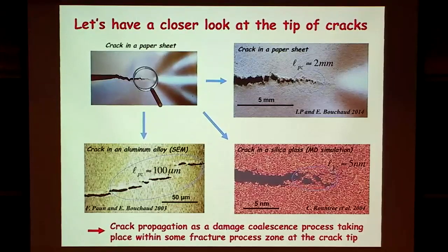Okay, I'll try to answer Srikanth's question. I guess when you look at these damage drops, they are random, I mean, the structure on them is random. However, once a damage front has appeared, or a damage drop has appeared, the next one is correlated, and the next one is correlated with it. Therefore, on scales much larger than these drops, you have correlated exponents, whereas under that scale you have just the random thing of the local structure. This is why you have the change in exponents physically.